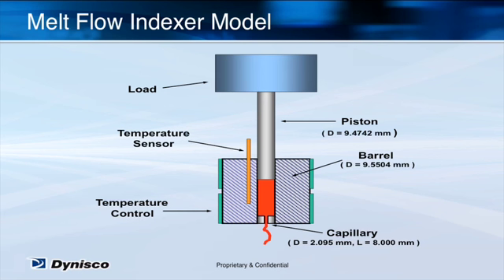MFI is a measure of the ease of flow of the melt of a thermoplastic polymer. It is defined as the mass of the polymer in grams extruded in 10 minutes using a specified test method such as ASTM D1238 or ISO 1133. In the method, polymer is heated to a defined temperature. Then it is driven through a capillary with a defined diameter and length by pressure created by loading a piston